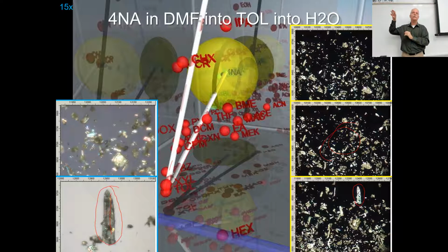We set the same temperature, the same pressure, the same speed on the motor, and so on. This happened at a company I worked for in the past, where they synthesized these molecules and got the right crystal structure at a previous facility. They built a new facility, and they're all excited. We've got updated electronics, updated controls, updated motors and everything, and it could not get the same crystal structure.